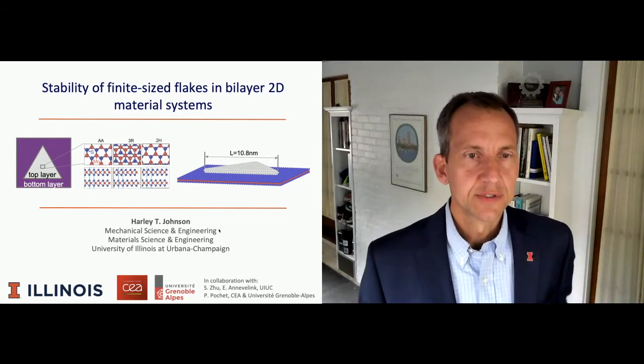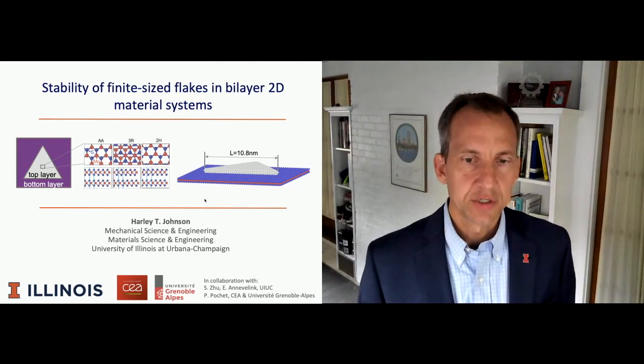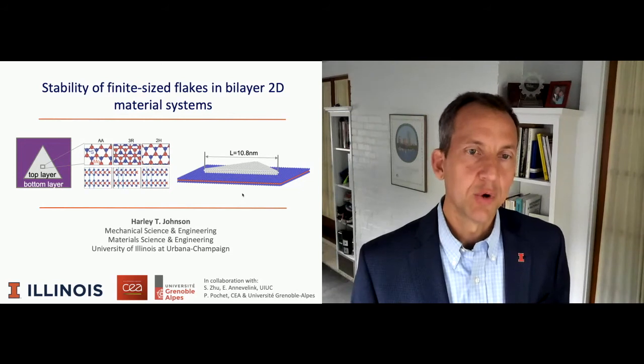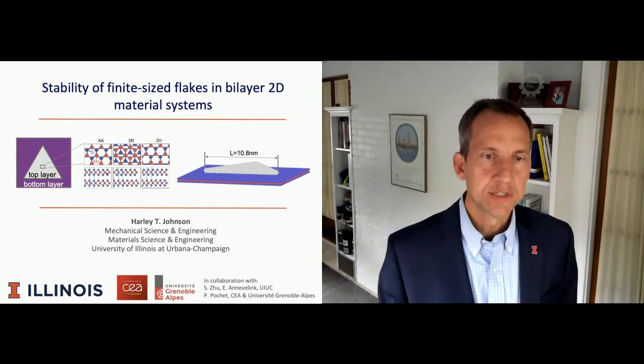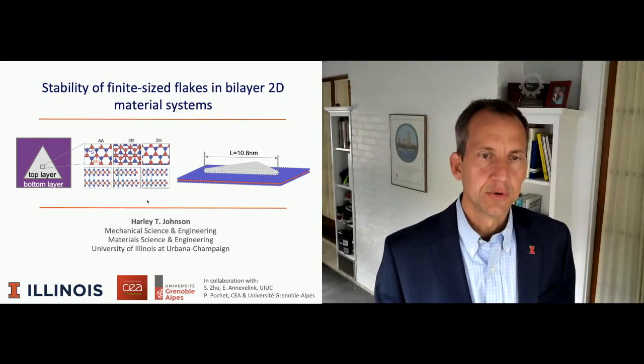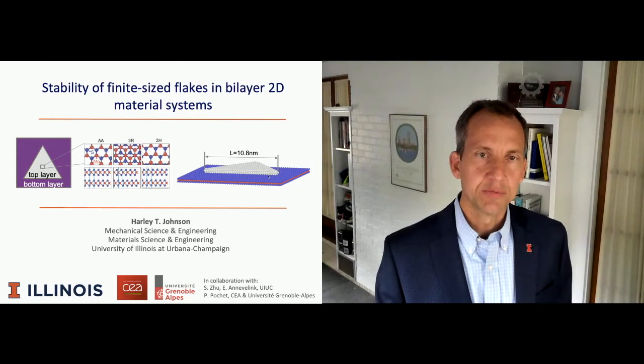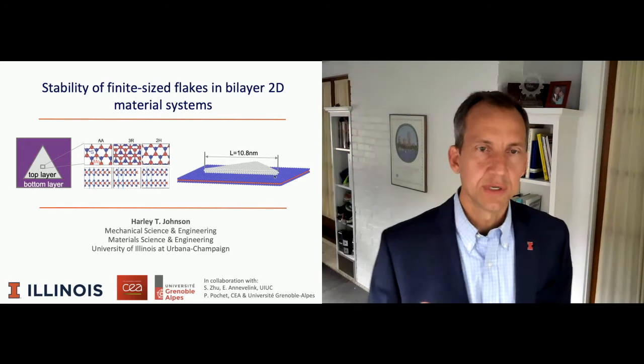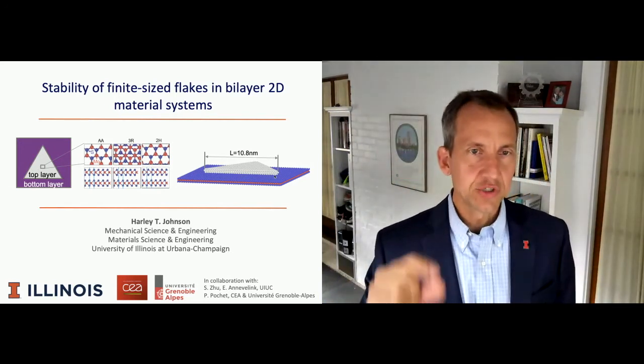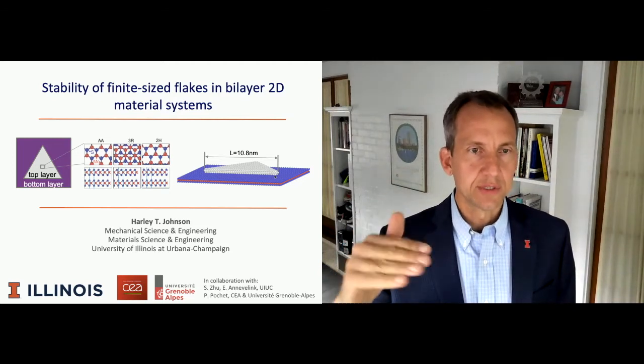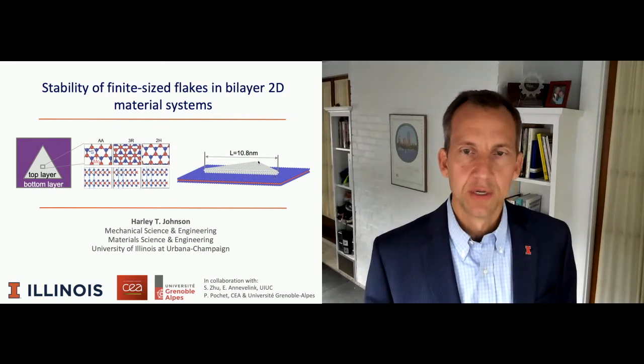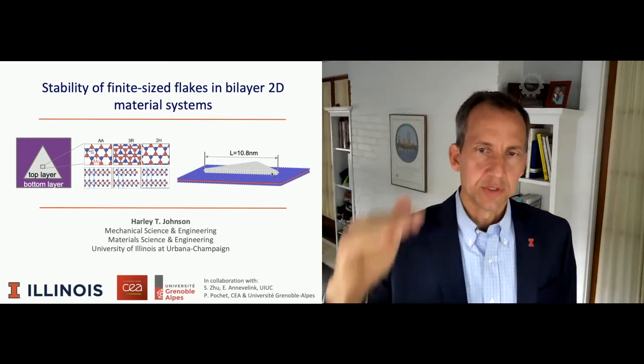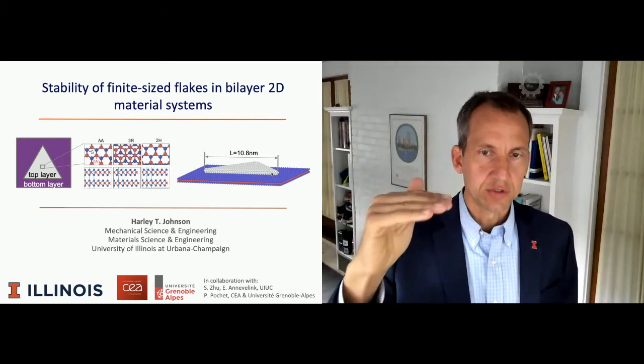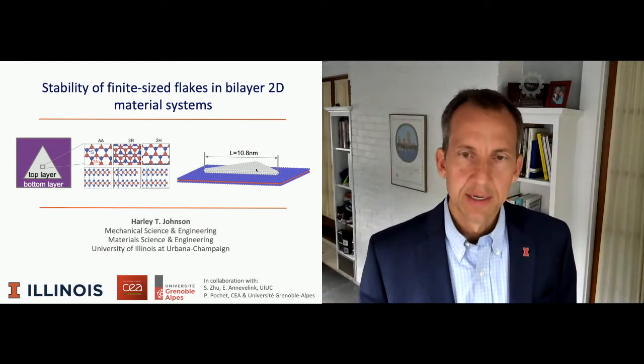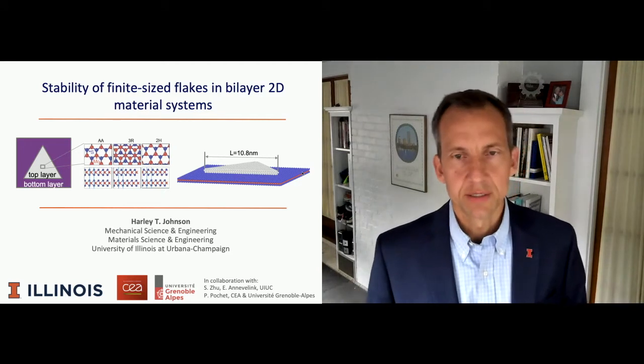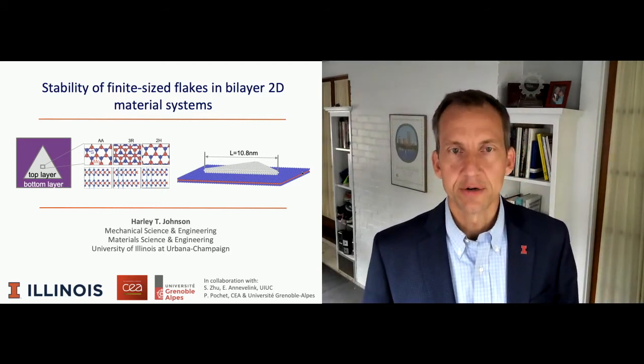So on to the technical part of the presentation. What's shown in the title slide here is just an image from a calculation that Shuzhe did on bilayer MoS2 systems. And the MoS2 structure is illustrated in this sketch. We call it a bilayer, and we refer to MoS2 as a 2D material. But in fact, MoS2 has a complex structure. In each layer of MoS2, you really have 3 layers of atoms: 2 sulfur layers and a molybdenum layer. And so the top MoS2 structure is a triangle shape. That's what we refer to as a finite size flake. And the bottom is a larger substrate, if you like. But this essentially is what we are calling a bilayer of MoS2.